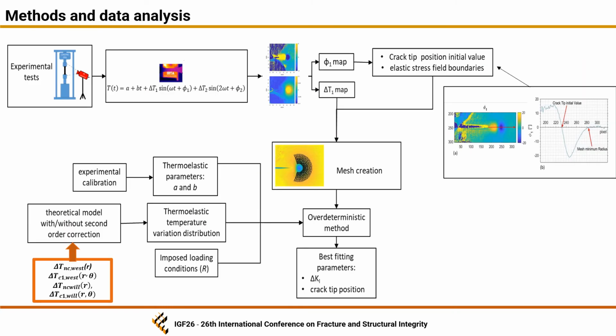This slide represents the workflow of the procedure. In this case, after the experimental test and lock-in analysis that decomposes the signal into the thermoelastic phase shift, which allows obtaining the crack tip position initial value and the elastic stress field boundaries, and the thermoelastic maps that are included in the implementation of the over-deterministic least square fitting method.